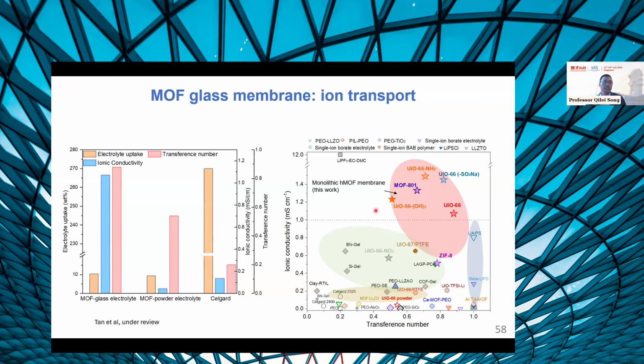I have to explain that this is not a solid-state battery, so this is not a solid electrolyte. This is a semi-solid or quasi-solid electrolyte, because the MOF membrane, the MOF separator, absorbs a little amount of electrolyte. So this is like ion exchange membranes, right? The absorption of this electrolyte can form ion transport channels that can facilitate the transport of the ions, especially in the battery.